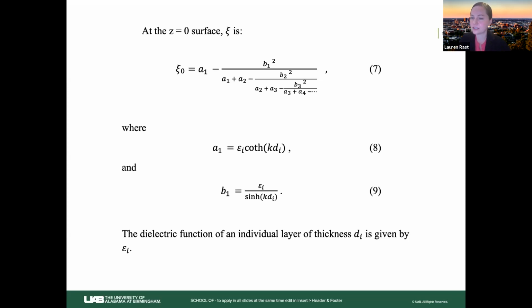And this expression was found for electron energy loss spectroscopy in this reflection geometry. But it's been shown that it applies for electron energy loss spectra for phonons that we discussed earlier, surface plasmon polaritons, and a lot of different quasi-particle collective modes in these multi-layer heterostructures. So the idea is that we have these interacting interfaces in this sandwich structure, and we're able to find the overall dielectric function from this expression.